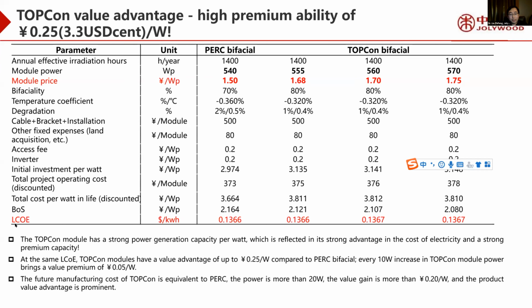Now we assume the same LCoE is 0.136 yuan per kilowatt hour. And in this LCoE, the module price of PERC is 1.5 yuan per watt. And if we get the same LCoE, we can find that the TOPCon modules' price should be 1.68. If module power is 570, the module price should be 1.75 yuan per watt. This means that TOPCon modules have about 0.25 yuan per watt additional price, additional value gain.